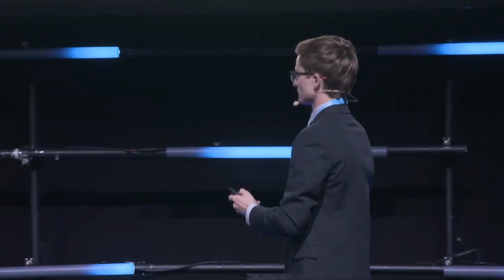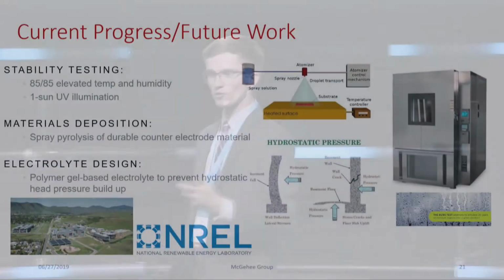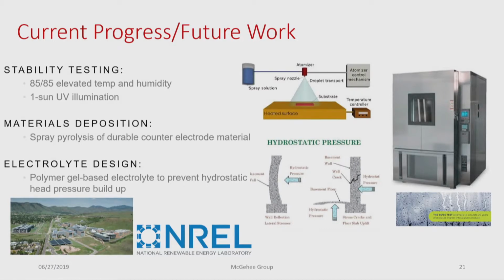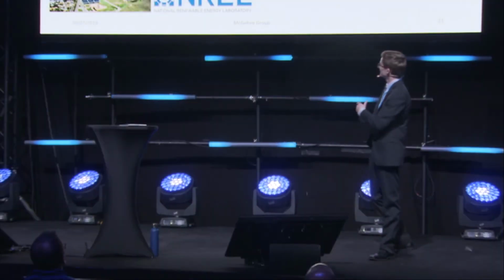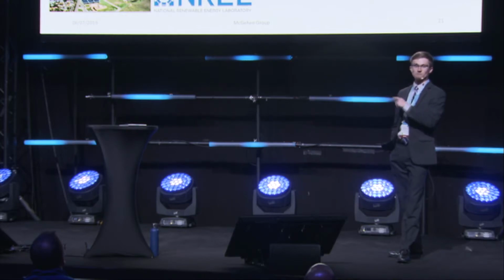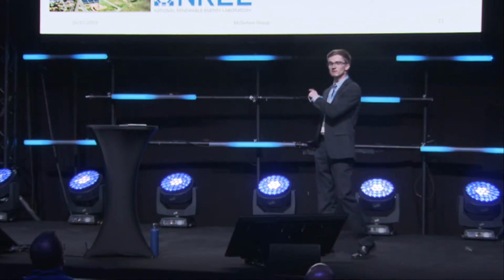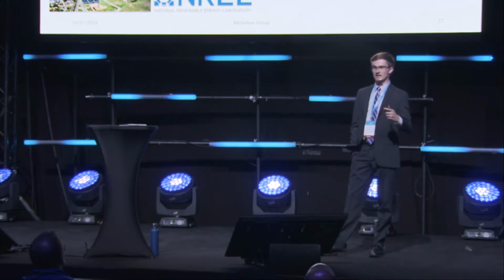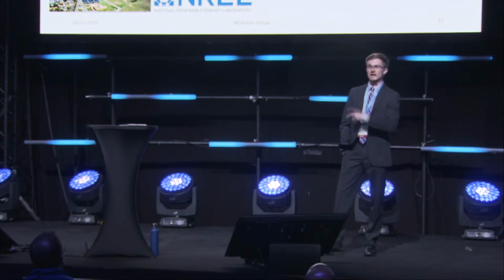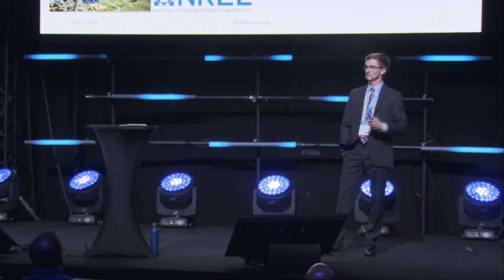In addition to tackling the durability and scale issues associated with this technology, we have a couple other active projects to get a realistic understanding of potentially implementing this technology worldwide. One is that our lab recently moved to Boulder, Colorado about a year ago. We're doing some elevated temperature and humidity testing, in addition to testing our electrolytes and our seals under one sun illumination. What's great about being located in Boulder is that we're only about 40 minutes away from the National Renewable Energy Lab, commonly referred to as NREL, in Golden, Colorado. This is the facility in the United States that runs all the ASTM testing for dynamic windows. So we're in the midst of putting our windows in their testing chambers to test them at elevated extreme weathering conditions.